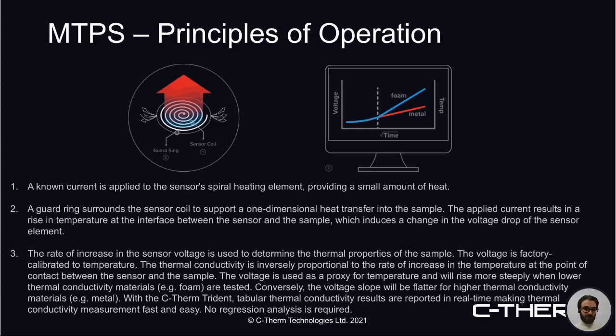Jay did mention this earlier, but I'll focus on it a little bit here as well. The guard ring is essentially a technology that's only available on the MTPS, and it surrounds the entire contour of the sensor itself. When that initial sensor fires or initializes for the measurement, the guard ring will initialize simultaneously. What this does is prevent any lateral heat loss from occurring. So your measurement is always going to be directionally dependent, going into the material that you're testing. This will depend on the way you're orienting the sample on top of the sensor to determine the direction of that measurement into your sample. It will always be normal to the sensor surface.